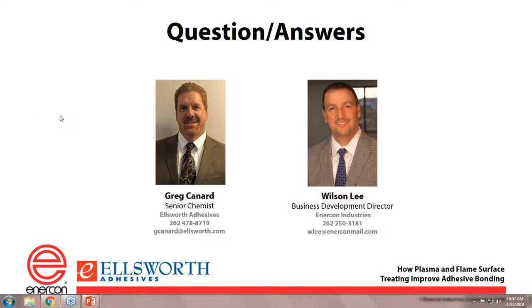Wilson, a couple of people have a question related to what's the difference between corona treatment and plasma treatment? I don't know. Well, I do, but plasma is blown ions. So again, if I'm using compressed air, I've got hydrogen, I've got oxygen, I've got nitrogen in there, and I'm taking the percentages there and changing them into ionized gas that's blowing onto the surface. Corona is more of an electrical stimulation of the surface.